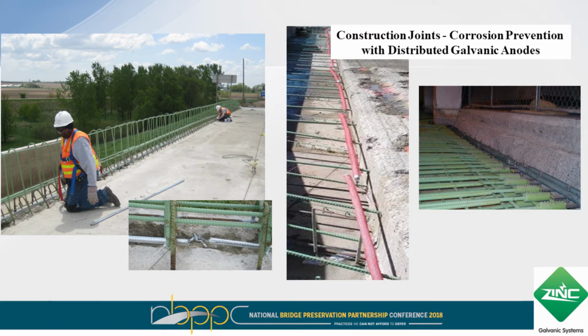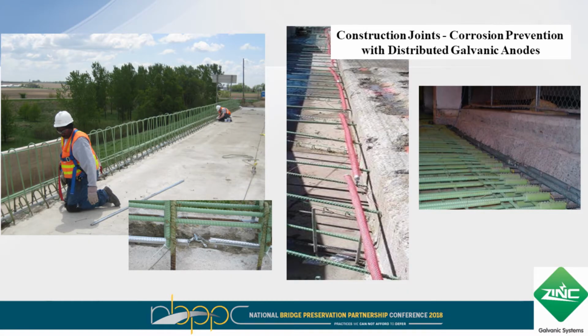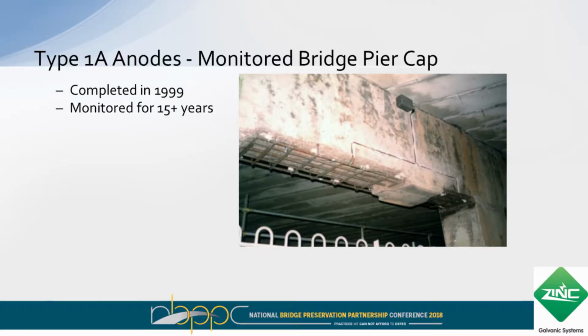And we saw a presentation from earlier today from Brian Pales about corrosion activity occurring at cracks in construction joints. So in this case, this is a bridge widening project where you may or may not have really active corrosion at this point, but you're leaving a construction joint in place, and you can see some anodes just placed right at that interface between the new and old section. In some cases, you can move to larger anodes for the construction joints using more distributed anodes.